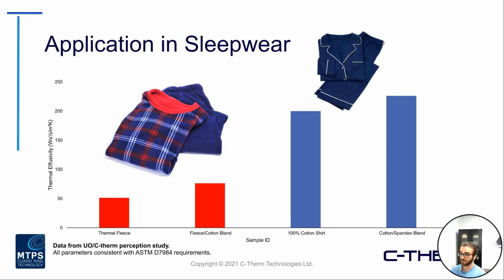And then on the right side, you can see those higher effusivity values coming in. So 100% cotton, a cotton spandex blend coming in at a much higher effusivity, approaching more of that cool touch fabric. Again, these may be some of the materials you're putting away until next summer, as sad as that is to say. But the story you may be able to see here is the thermal fleece on the far left, obviously coming in at the lowest effusivity result.